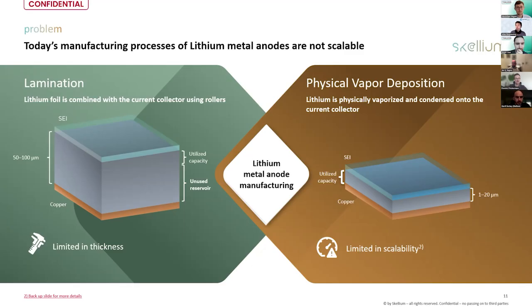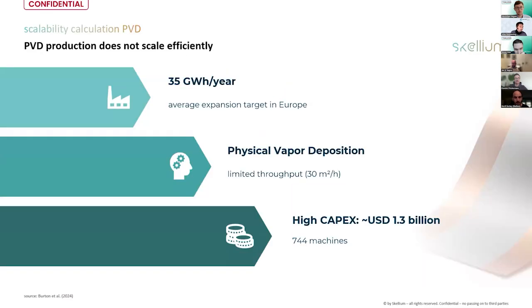And scalability is most of the time a buzzword that everybody just throws into the room, and nobody asks about it. But what does this actually mean? So when we look into 35 gigawatt hours of a European production plant, which was more or less the standard production for Europe for 2030 in the past, with an average physical vapor deposition equipment, you need 744 machines for producing the lithium metal electrodes for this, which is around 1.3 billion of capex. So therefore, I would say we can put a tick behind it that PVD processes are not that scalable.